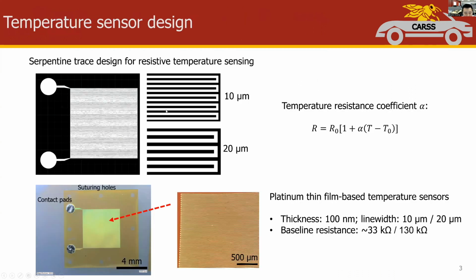To measure temperature, we propose a thin film temperature sensor that uses platinum metal. The reason is that resistance of metal can change linearly with temperature, and the rate is defined as the temperature resistance coefficient. We designed both 10 micron and 20 micron platinum lines, which are patterned in zigzag structure using lithography and lift-off process. The sensor's area is about 1 by 1 centimeter, and the active sensing area is about 5 by 5 millimeter, as you can see from the bottom.